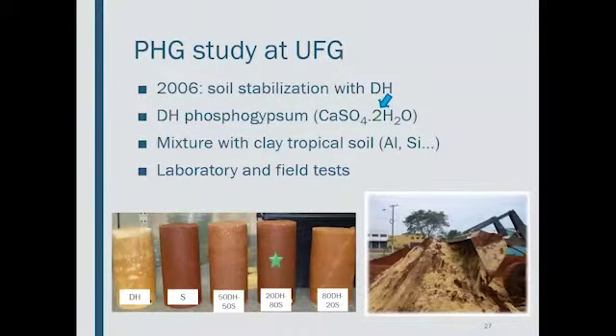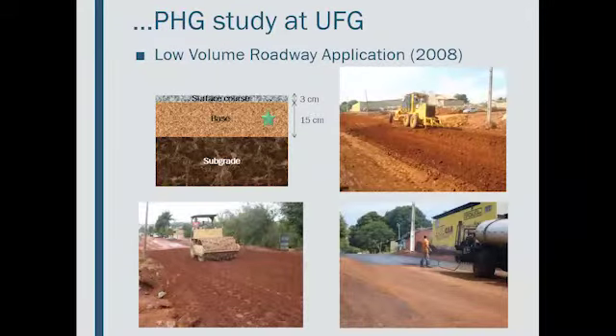Then we started to study this material in 2006. We thought about using phosphogypsum to stabilize soils. The phosphogypsum that we have there is the dihydrate type. And the most abundant soil that we have is the tropical clay soil. Then we performed lab and field tests. In the lab, we found that this dosage is a good start to get better mechanical behavior. And we used this mixture to construct a low volume road, using it in the base.